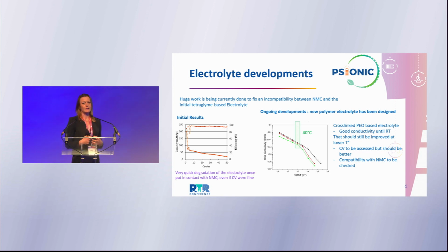And PEO is not stable against NMC, so we also need to make changes in terms of chemistry to make it happen. So on the left, you can see the first results with the basic electrolyte. It was not working at all when we put the NMC cathode in front of this PEO electrolyte. So we had to change the chemistry inside to make it functional.